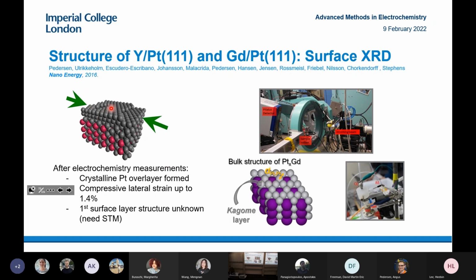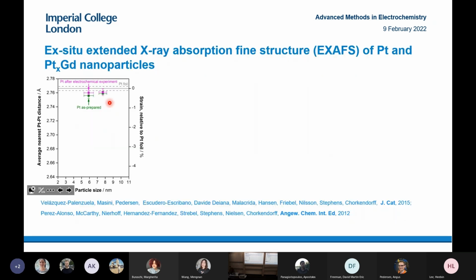Of course, we're only measuring the platinum distance in this overlayer. We never measure that at the surface. To do that, we have to do STM. More recently, the group of Alexander Bandarenka has done that and found that the platinum distance at the surface from STM was actually slightly compressed. We also did XAFS of platinum gadolinium and platinum yttrium nanoparticles. There we can measure the overall platinum distance in the nanoparticle, not necessarily at the surface, which is the catalytically active part, but we can still measure our overall strain.